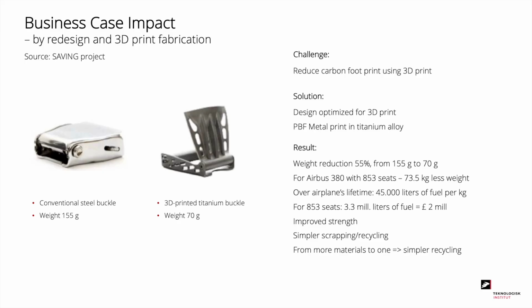What was gained by that? Well, the result was a weight reduction of 55%, from 155 grams to 70 grams. That's not much, you can say, but for an Airbus 380 with 853 seats, it sums up to a total weight reduction of 73.5 kilos.